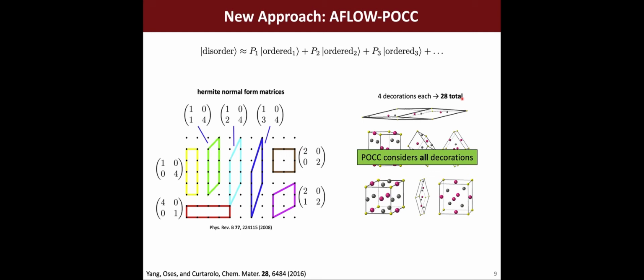softwares that do variations of what I'm talking about today, but for instance, they will only decorate based on this uniform expansion supercell. They won't consider the various different supercells with different skewed directions. And those cells are going to play a very important role in determining the energy spectrum within which we can describe the stability of disordered materials. So keep that in mind. We really need to explore all the possible decorations. I'll discuss in a few slides why that's important.